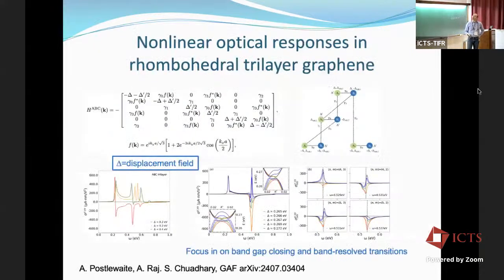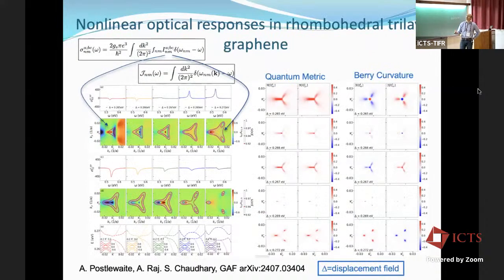So in the final bit of the talk, because I think I'm just about out of time, we looked at the nonlinear optical response of rhombohedral trilayer graphene. And we saw a similar sort of thing. There was a band transition in the system, which led to a sign change in the optical conductivity around a particular frequency. Our objective here was to see what we can say about the quantum geometry of the band structure. In the previous example, we could see topological properties of the band structure. Here, we wanted to see more generally what we can learn about the quantum geometry, the quantum metric, the Berry curvature, of the band structure where there are sign changes in the optical conductivity.